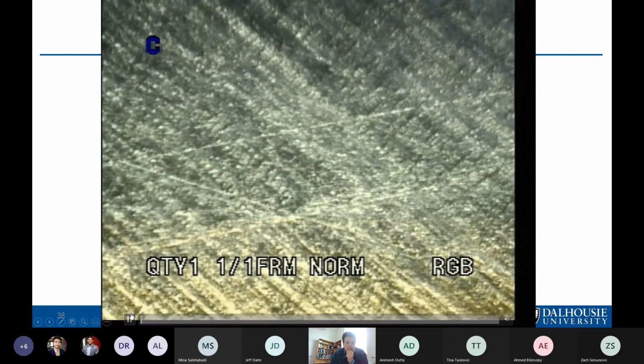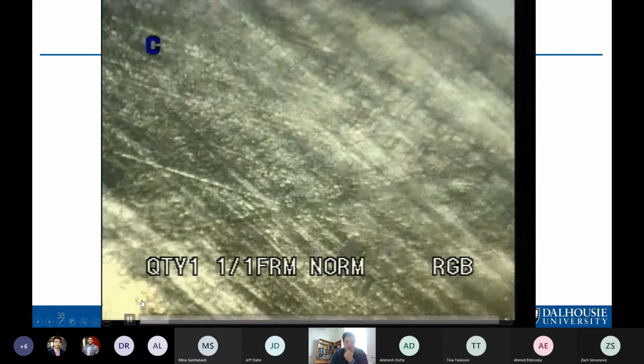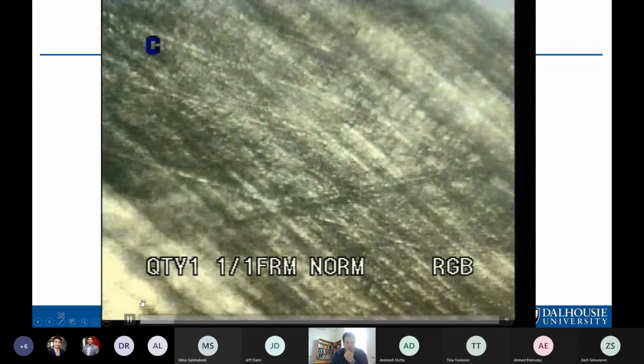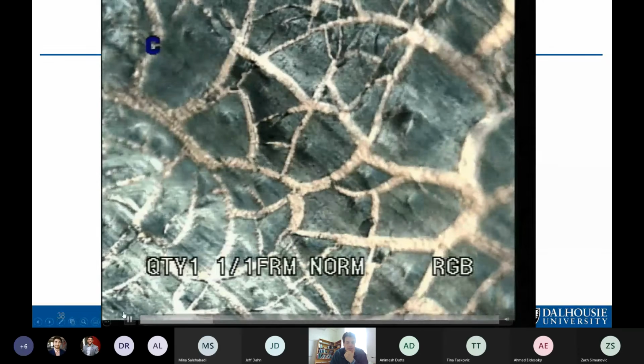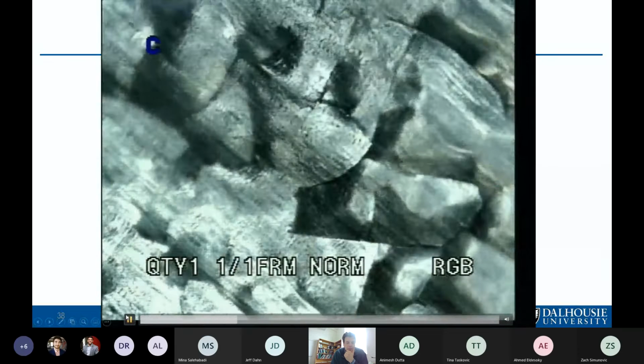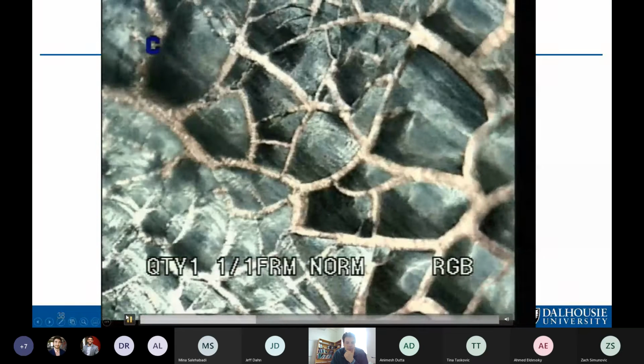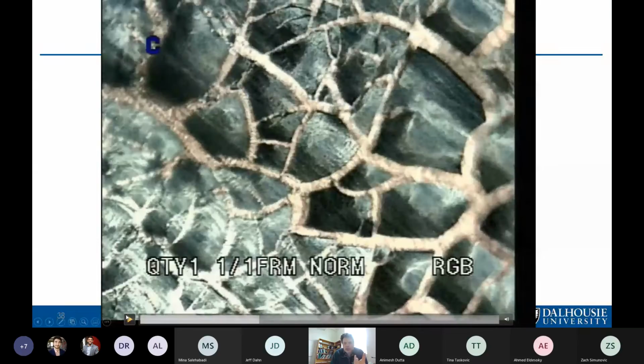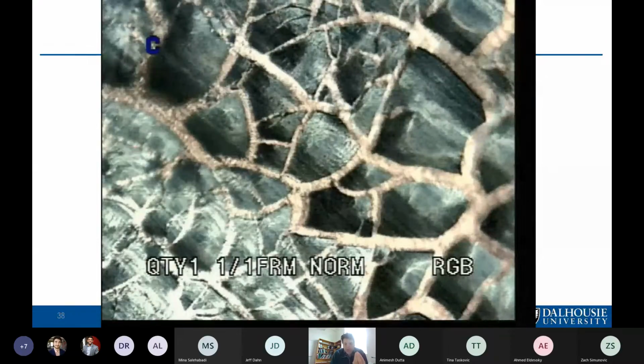Boy, I can just barely click on that. So now the film is expanding as it's being lithiated, it's expanding towards the microscope, and then it contracts. And this, yeah, I should pause it. So during contraction, the film can shrink in all directions, but it's held by the substrate underneath. Still, it's pinned by the substrate. And so that's why it's cracking. It's cracking because of these mechanical interactions with the substrate and not because of two-phase regions.